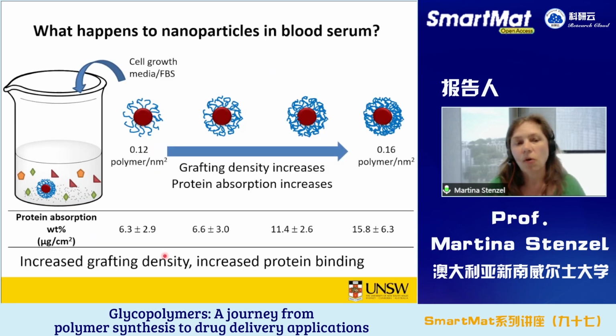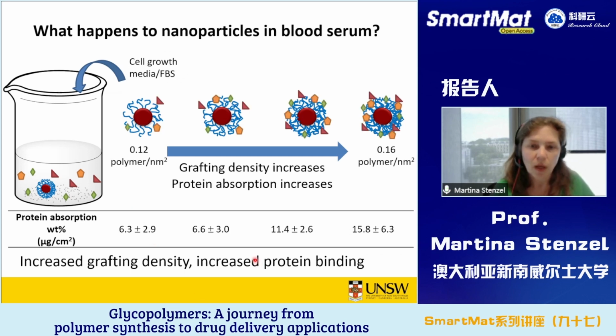Now we wanted to learn how protein binding changes. We incubated these nanoparticles with serum protein, and after that measured the amount of protein. What you can see here is that the higher the grafting density of glycopolymers around the surface, the higher the amount of protein attached. So lower grafting density, interestingly, leads to lower protein absorption. This is not always the case. Very often higher grafting density can lead to less protein absorption. But in our case here, we found there's very much a difference: more grafting density, more protein absorption.